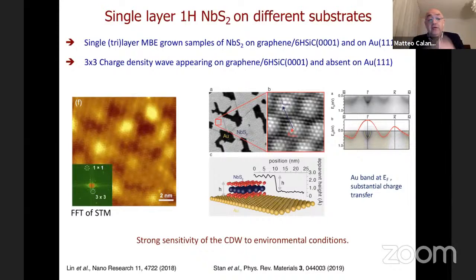And this is the one I showed you at the beginning in the first slide. I will show you again soon that the harmonic calculation failed completely and gives you a charge density wave. So if you take the single layer, the situation is very puzzling because they can be grown on graphene on top of 6H silicon carbide, or they can be grown on gold 111. And in gold 111, there is no charge density wave. And if you grow it on graphene on silicon carbide, there is a charge density wave.